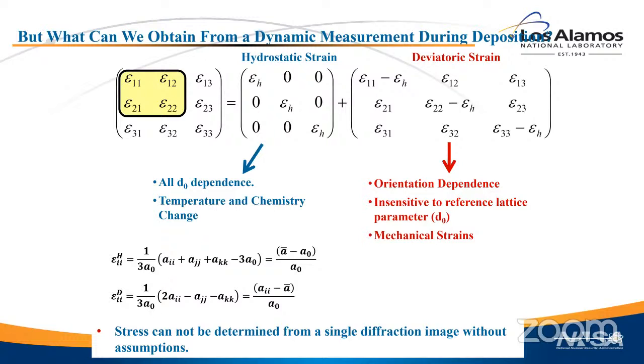Well, not only is it separable mathematically like this, but it's also separable in terms of physics. And we've talked about this. The deviatoric strain is all of the orientation dependent part, right? So that's where all the mechanical strains show up, stress. The hydrostatic strain is the temperature and chemistry. So you can separate it both mathematically and in terms of interpretation. And that's what lets us pull out microstructural features from an effect that's pretty convoluted.